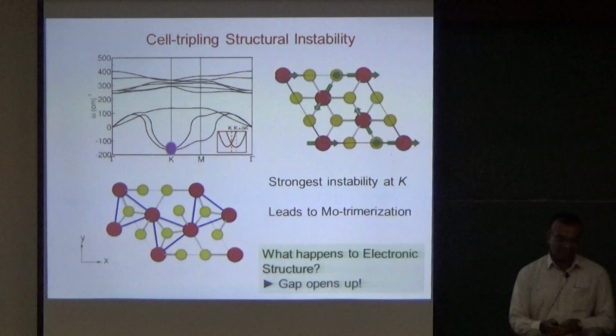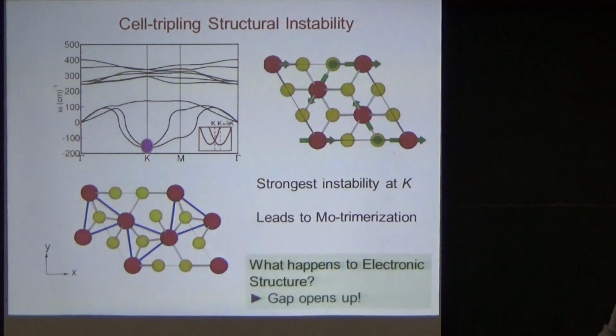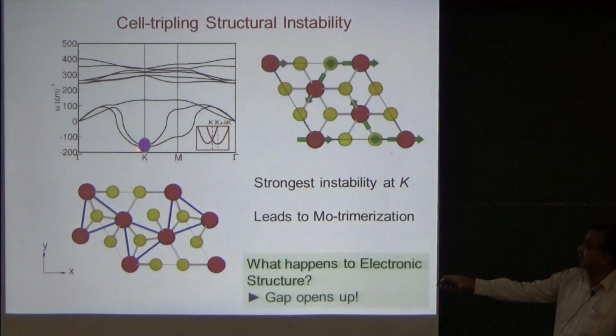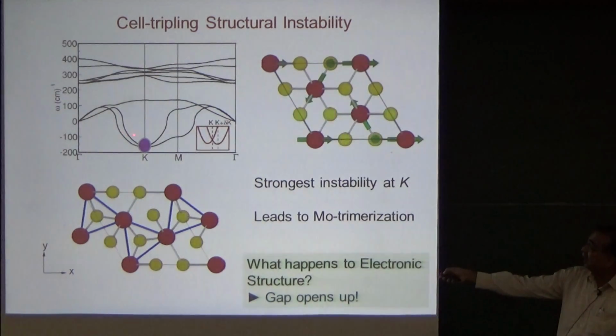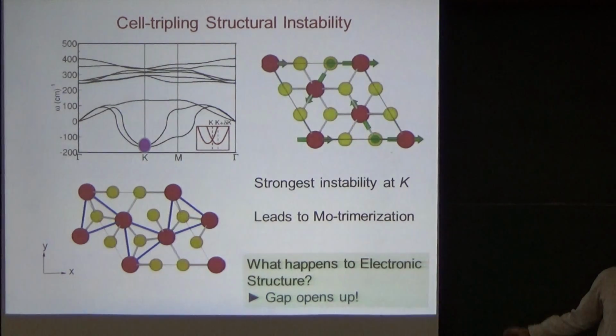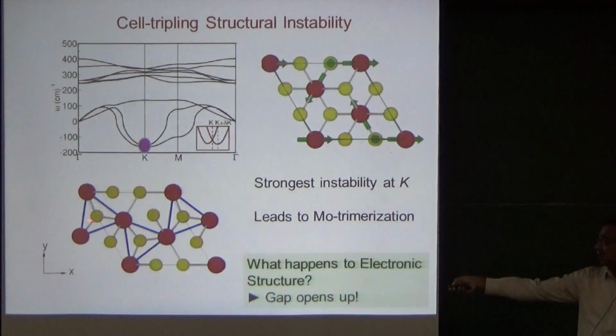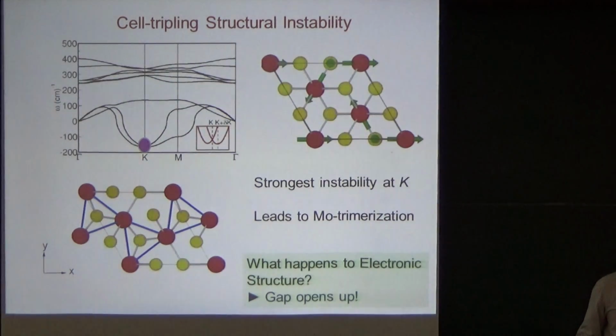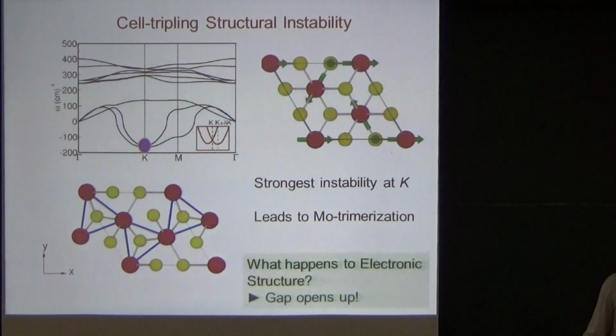Let me explain what is happening. See, if you look at the phonon dispersion of the 1T structure, there are two important instabilities in it. One is at the K point and one is at the M point. If you have the K point instability, which is the strongest as in MoS2, you get ferroelectricity. That K point gives you this trimerization. The M point gives you a root 3 by 1 type of structure, which doesn't break inversion symmetry. So that's what happens in ReS2. So you are absolutely right, ReS2 is also a distorted 1T form, not a pure 1T form like the one I had. Yes, people have tried to dope MoS2 with Re to stabilize the 1T phase, using rhenium substitution in molybdenum sulfide.